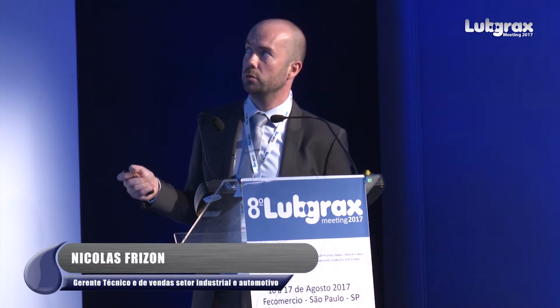But in red, you have the traditional base stock for this application, which is a trimellitate. And if you see here, this curve shows that in these conditions, you have a very high volatility, which isn't really good because your chain isn't lubricated anymore. So we changed this formulation and we chose a neopolyol ester in blue. And as you can see, it begins to have a better volatility. You have a higher amount of product and slow decomposition and better residue at the end.